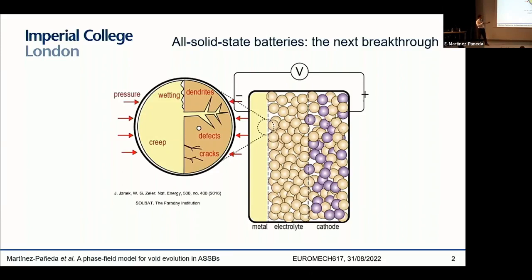However, mechanical instabilities at the lithium metal solid electrolyte interface are hindering the uptake, the viability, the commercialization of these solid state batteries. And so there's a lot of exciting and puzzling mechanics phenomena happening here. Particularly problematic are these dendrites, these needle-like filaments that originate at the interface between the lithium metal anode and the ceramic electrolyte, and that propagate all the way into reaching the cathode and causing the short circuit of the battery, so the cell death.